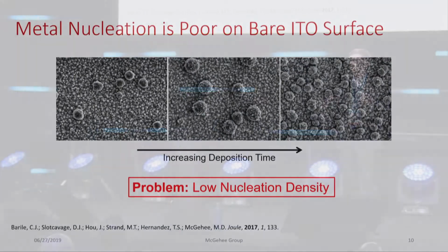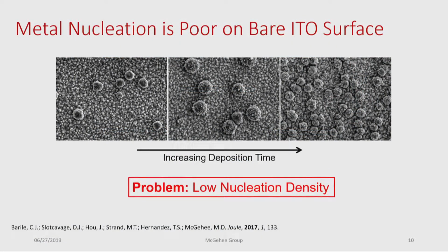Specifically, metal nucleation on these TCO surfaces is extremely poor. So the most commonly used TCO for these applications is a mixed metal oxide. It's actually a tin-doped indium oxide, commonly referred to as ITO. And ITO has some very interesting heterogeneous surface chemistries that cause metal nucleation to be very poor. Now, some of you may be thinking this actually is really not that big of a deal, but it becomes substantial when you try to scale this technology.